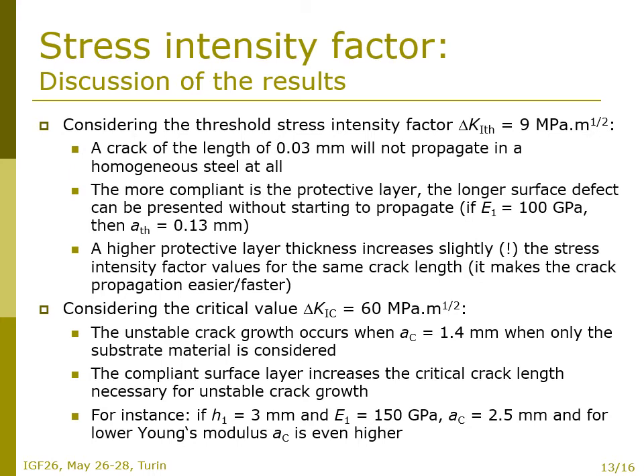Considering the critical value of 60 megapascals square root meters, the unstable crack growth occurs when the critical length of the crack is equal to 1.4 millimeters, when only the substrate material is considered. The compliant surface layer then increases the critical length necessary for unstable crack growth. For instance, if the layer has the thickness of 3 mm and Young's modulus of 150 gigapascals, the critical length of the crack is equal to 2.5 millimeters. Of course, for lower Young's modulus, AC is even higher.